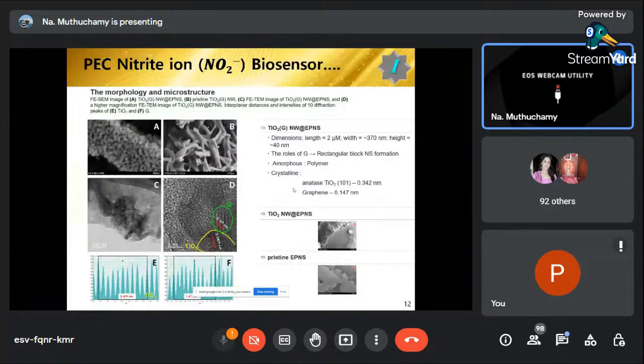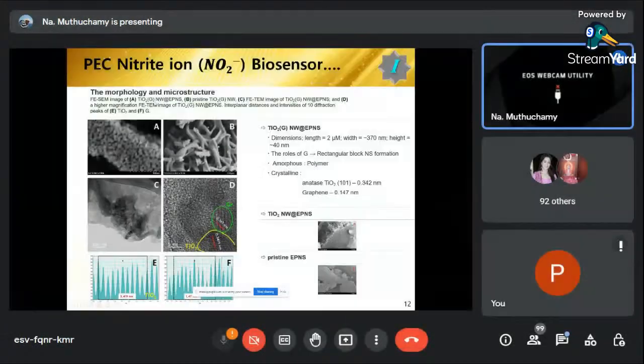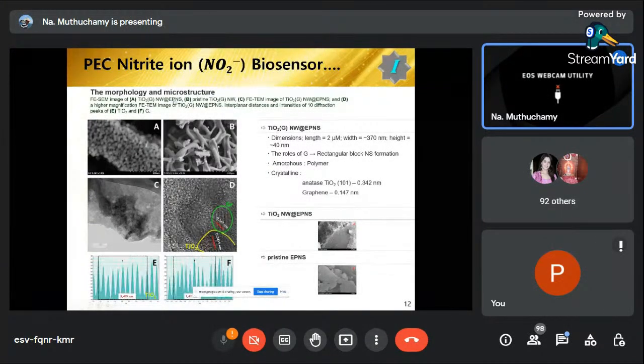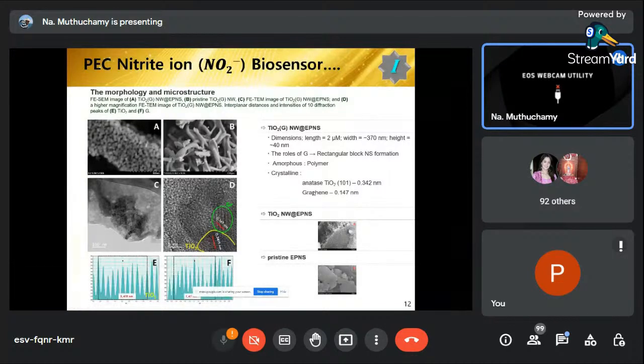Here are some basic morphology studies. You can see the sponge-like structure of the prepared TiO2 graphene nanowire electroconducting polymer nanosponge. We have to confirm whether only the TiO2 graphene nanowire shows a sponge-like structure or not. So we prepared it without polymerization also. You can see it shows only the nanowire structure. The nanosponge shows a combination of graphene, TiO2 and polymer. You can see the amorphous surfaces are the polymer, and the graphene shows its fringes, and TiO2 also shows the same things.